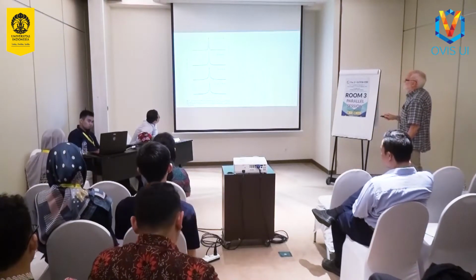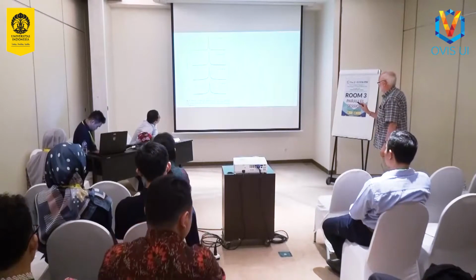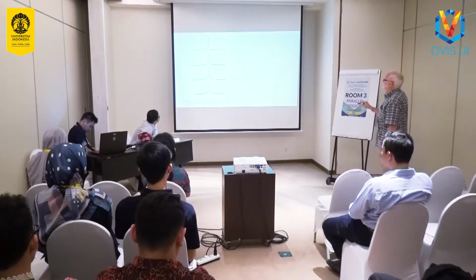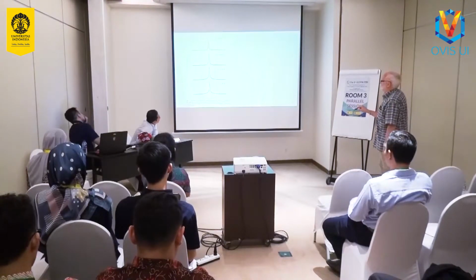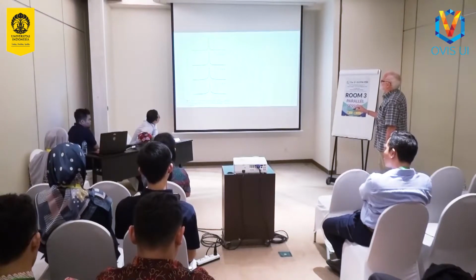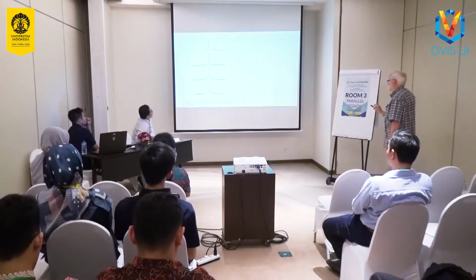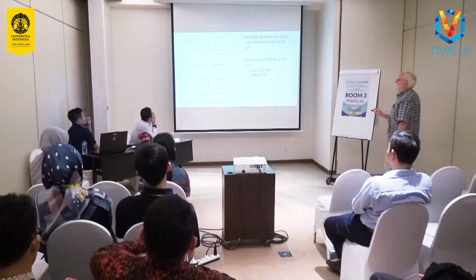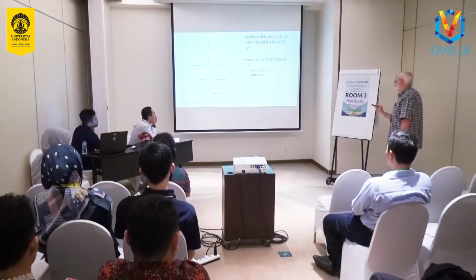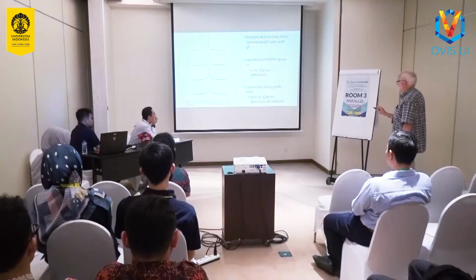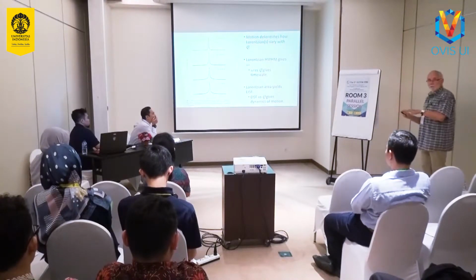Well, here's methanol in zeolite hydrogen Y. We saw the INS evidence that it was hydrogen bonded, and you can see, very clear on this slide, the different values of Q, because remember we can collect the spectrum at different angles, which gives us different values of Q. The line is broadened. The sharp thing here in red is the resolution function, and there is a broadening here which depends on Q. At different angles, there's more or less broadening. So if we measure the half-width of the line versus Q, that'll tell us how fast the molecule is moving. And if we look at the dependence of the integrated intensity of this broad component versus Q, that tells us the kind of motion that's taking place.